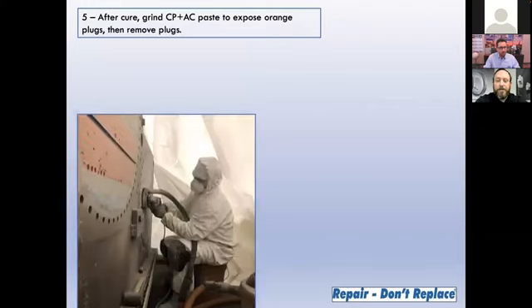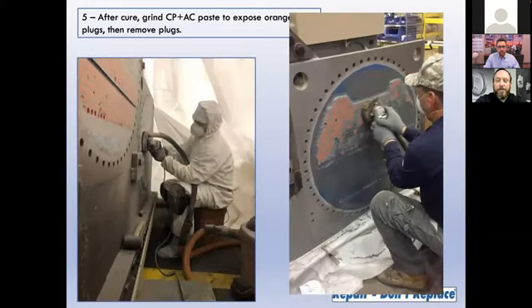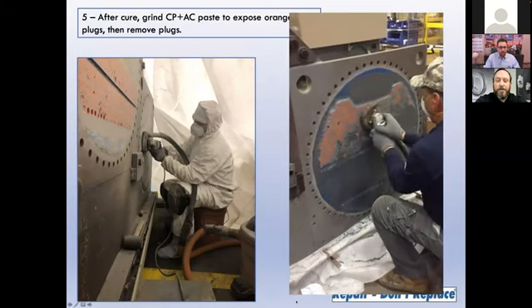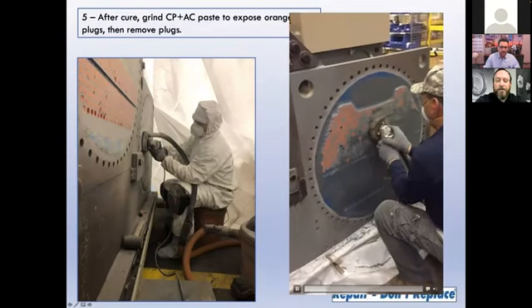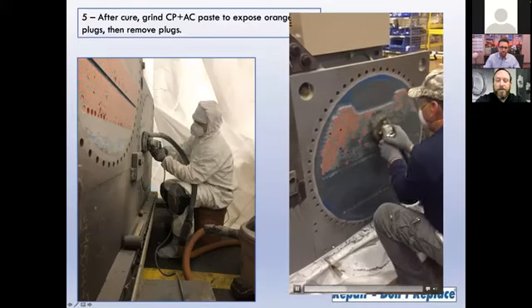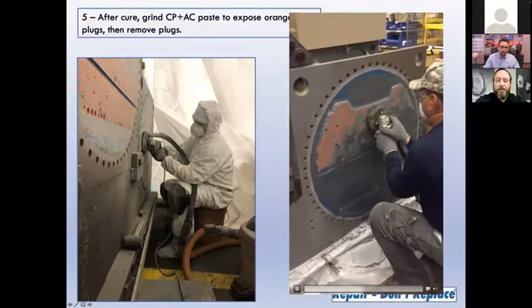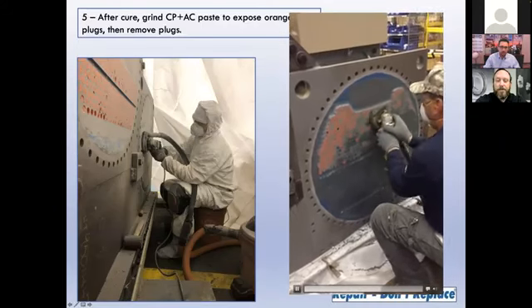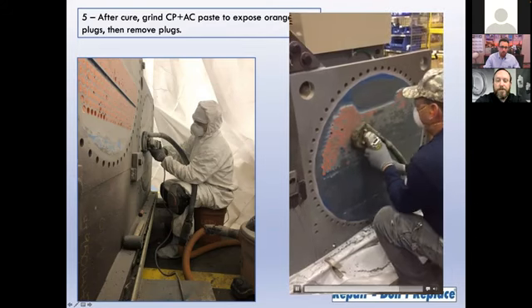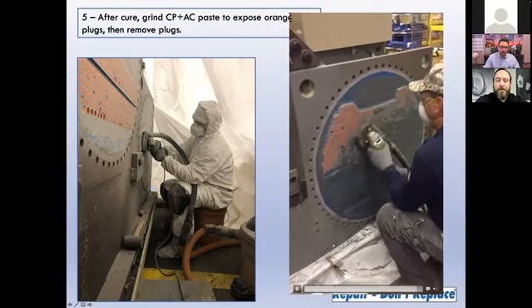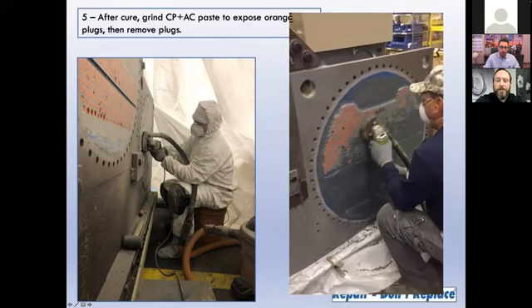Allowing the product to cure overnight, we typically come in the following morning and start the process of removing the excess Ceramaloy CP plus AC from on top of the tube areas, exposing the coating plugs. Once all of the coating plugs have been exposed, we will then remove them. And as you can see from that short video segment, having a little less material on top of the plugs goes a long way in performing the process and getting it done in a timely manner.